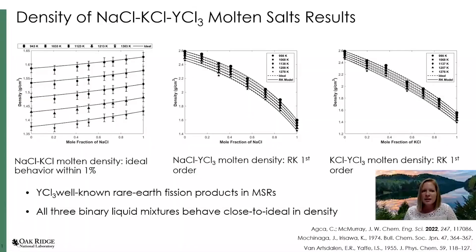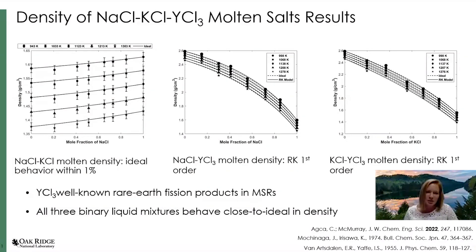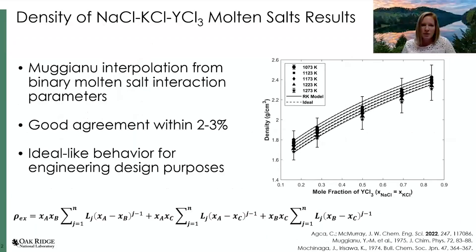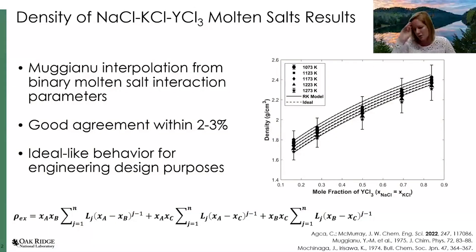Now looking at the density of the sodium chloride, potassium chloride, yttrium chloride pseudoternary — again, we're building complexity. We first evaluate each binary subsystem, and you can see the density of each binary subsystem in each of the three plots. It's a pretty good fit. But now, if you combine those subsystem models without any additional parameters, just using those building blocks, you can see that we get a good extrapolation of the behavior in the pseudoternary space, as shown in the example equation here.